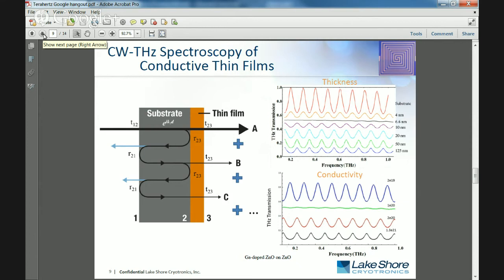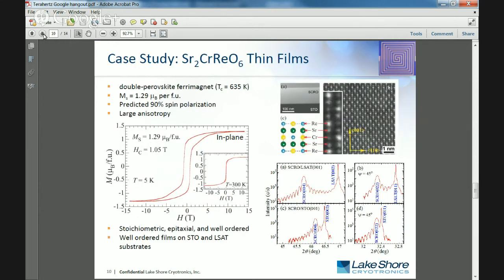And so if we pop over to the next few slides, I'll talk folks through where we found some utility in this. We've been doing some work with collaborators at Ohio State working with this material called SCRO, or strontium chromium rhenium oxide. It's an interesting material in the sense that it has some spintronic applications. It's a half metal that can polarize a spin current as it's passed through.